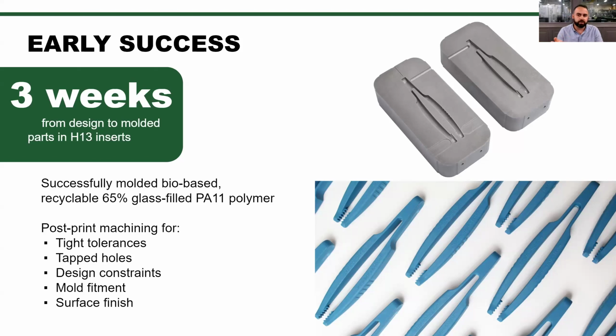Those cavities were actually molded at NPE a couple months back, so they're still going even with a 65% glass filled nylon, just showing that durability with the steel, which was one of the biggest differentiators we saw with this printer.